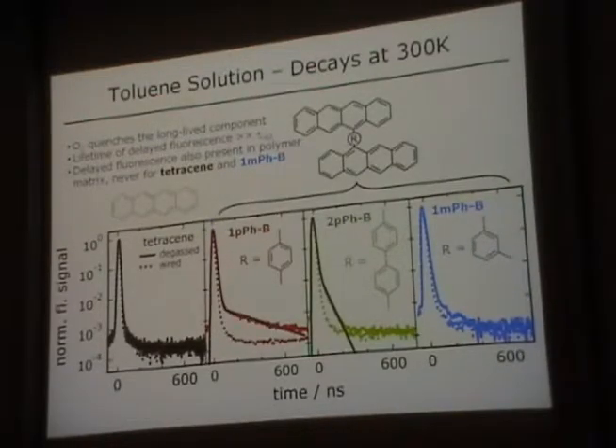So when you do these, look at the dimers. Tetracene, to make sure it's triplets, we add oxygen, right? Oxygen is a very nice triplet quencher. So you can sort of put oxygen in, take oxygen out, and that tells you, okay, this is not some other artifact or some baseline problem or something like that. With tetracene, no effect at all, right? There can't be exciton fission. There can't be triplet pairs of tetracene. It's just a molecule by itself.